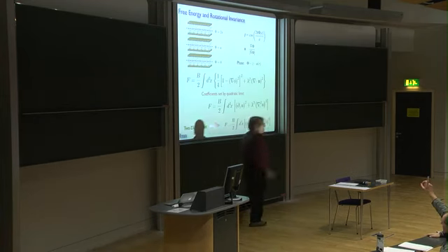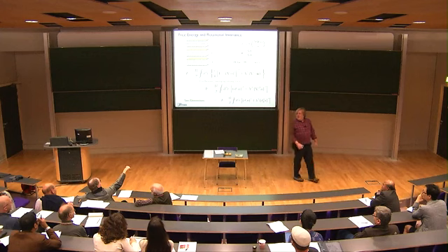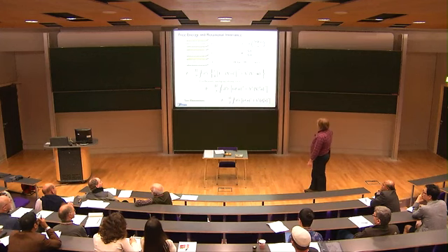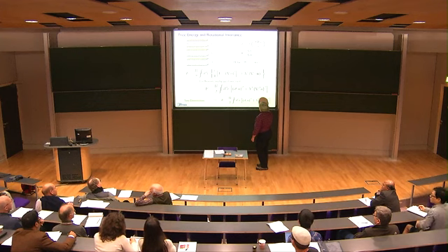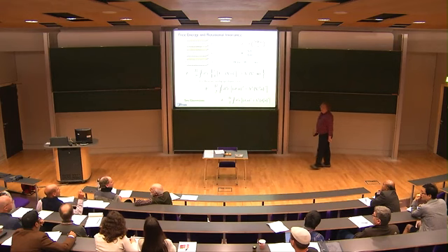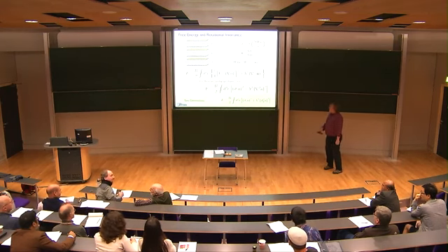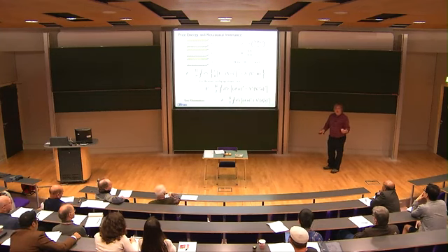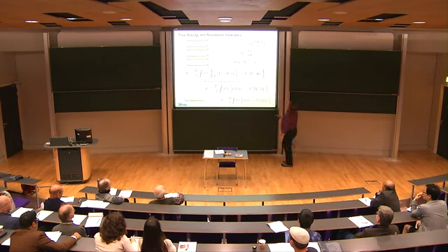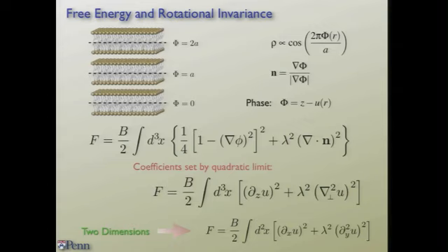Actually, there's one comment, which is that the leading order next nonlinearity is also fixed by the symmetries, as you know. What does that mean? The leading cubic nonlinearity, the dzu grad curve u squared term, its coefficient is B, up to a factor of 2. That's right. I agree. Yes, John says that rotational symmetry dictates that the cubic term, if you expand in powers of u, is also set, right? But I would say that I'm thinking of this as the whole strain. This is the whole strain field, right?